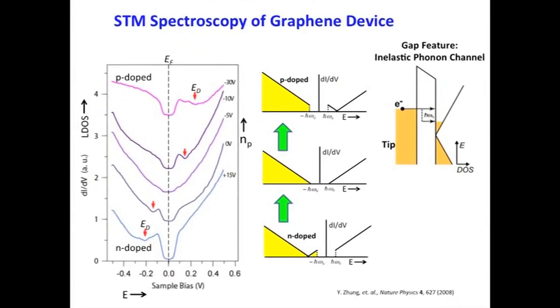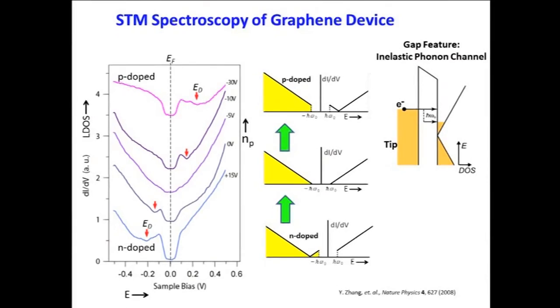Now, this gap-like feature is pinned to the Fermi level for different gate voltages, so that tells us that it's not a band structure feature of graphene. It's some kind of excitation, and what we believe is happening is that this is a sign of, it's not a true gap, but a sign of inelastic tunneling, phonon-assisted inelastic tunneling. The idea is that when we come to a bias here at about 65 millivolts, the tunneling electrons have enough energy to create a phonon, an out-of-plane phonon in the graphene, and that creation of that phonon helps to get the electrons in. So we get a big jump in the current due to this inelastic tunneling channel.